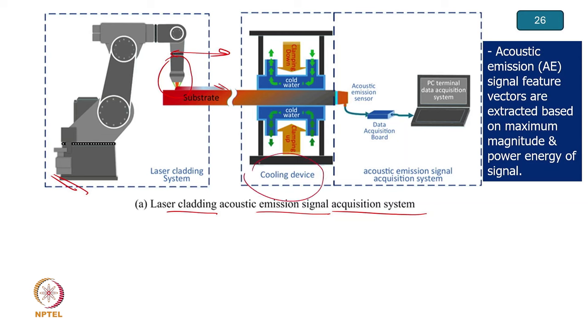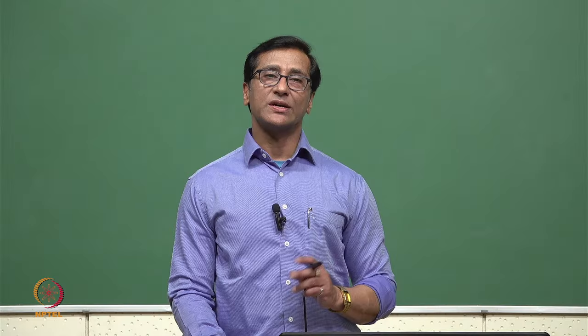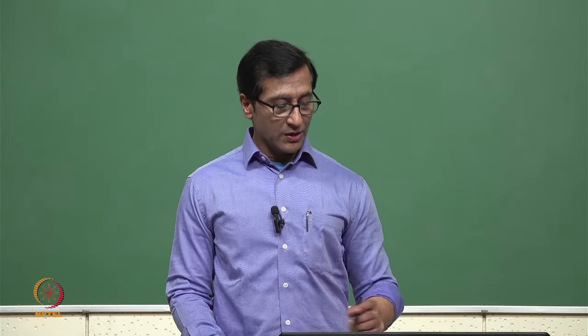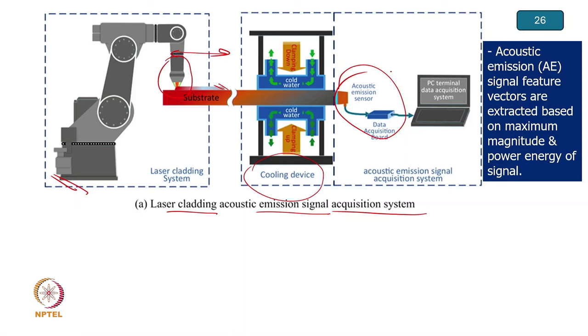They try to do cooling immediately so that there should not be much variation, because the powder and substrate will have a difference in expansion coefficient. If we do cooling much faster, then there will not be much problem. And whatever acoustic signal they are acquiring can be recorded, so simultaneous processing can be done. So that's why we say acoustic emission signal feature vectors are extracted based on the maximum magnitude and power energy.